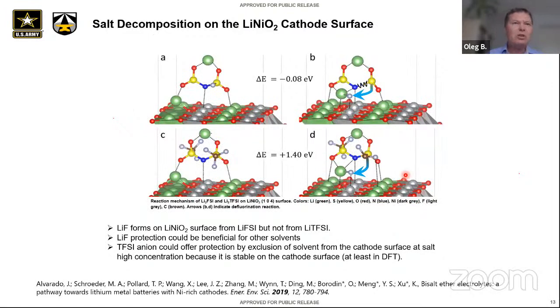What about anions? And that is a very interesting case, because I couldn't find decomposition of anions on the surface. We looked oxidatively, but what we found, on the other hand, if we go now to the fully lithiated surface and have an extra lithium on the surface, then there could be a defluorination reaction for the FSI anion, shown here, which is favorable. This reaction, however, is unfavorable for TFSI, which says that this reactivity mechanism is different. And if you want lithium FSI to decompose and form LiF on the surface to protect it further, as part of the more complicated CEI, then FSI is a better anion compared to TFSI. But on the other hand, if you want protection by having as many of the anions as possible on a cathode surface and excluding solvent, then TFSI could be a better choice. What about PF6?